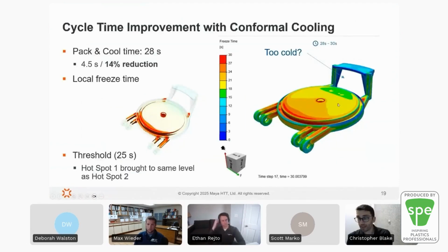So if we look at the freeze time estimate for this new design, we see that the overall cooling time has reduced to around 28 seconds, so by about 4.5 seconds. That's a 14% reduction, which means we actually have a non-negligible increase in our production throughput.